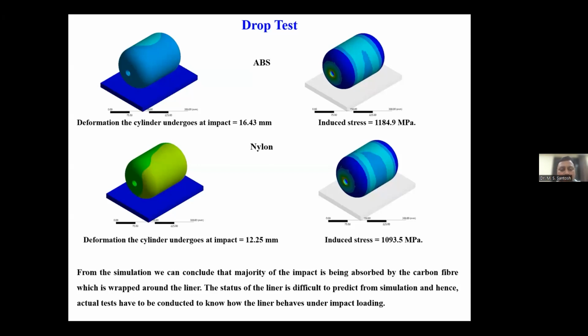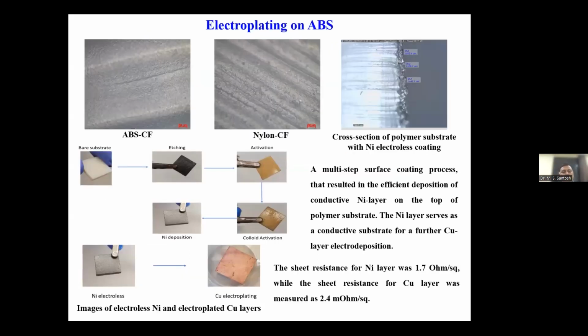In these drop test simulations, we were able to understand that the carbon fiber overlapping on the surface of the liner material was able to absorb most of the stress or the damage dent that is caused on the surface when it is dropped from a height of 10 feet through the simulation process. So the carbon fiber also plays a very important role, being overwrapped on the surface of the cylinders.